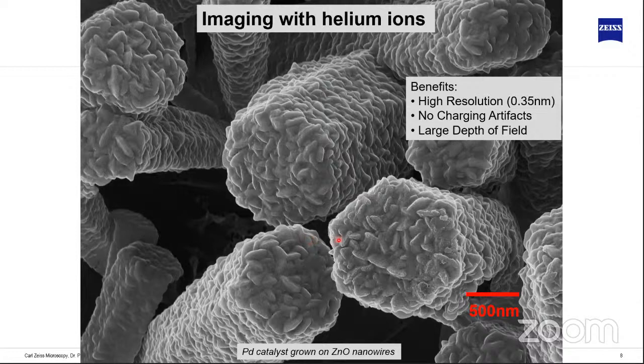And the other thing is that we do not observe any charging artifacts. The reason for not observing charging artifacts is the following. In an electron microscope, we always have the problem that depending on the beam voltage, we can have positive or negative charge on the sample, and that's very difficult sometimes to compensate. So typically what you do is you do either variable pressure imaging or you do low voltage imaging, but you're always around some equilibrium. With ion beams, it's very easy. We only can put positive charge onto the sample, and we can easily compensate that with an electron flood gun. So that means we can image all kind of samples in their native state without coating them, glass, plastics, biological samples, just image them and use the electron flood gun to compensate for the charge. So we can basically image everything without charging artifacts.